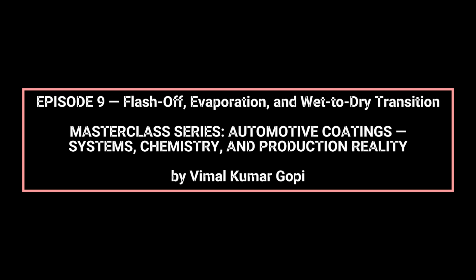At the process level, flash-off time, airflow, temperature, and humidity directly influence solvent partial pressure gradients. Increased airflow accelerates surface evaporation, while high temperature reduces solvent viscosity, but can also collapse the evaporation window. Humidity further complicates this behavior, especially in basecoats, where moisture can alter solvent activity and resin mobility.